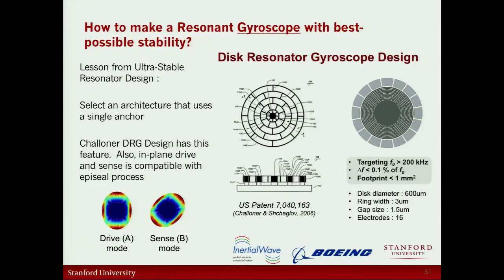So it's a flat disk of silicon with a lot of slots in it. And you drive it in plane in a mode that looks like the wine glass vibrational mode, sort of like this. And if there's a rotation around the vertical axis, Coriolis force couples the energy of that vibration into an orthogonal mode that's 45 degrees away, also in plane. And the whole thing has a single anchor right at the center. It's all in plane drive and sense. Could be made out of single crystal. It fits exactly into our process, and we've been having a lot of fun building these things.